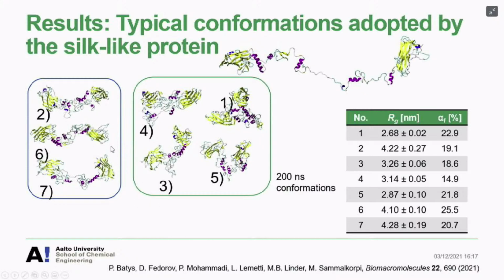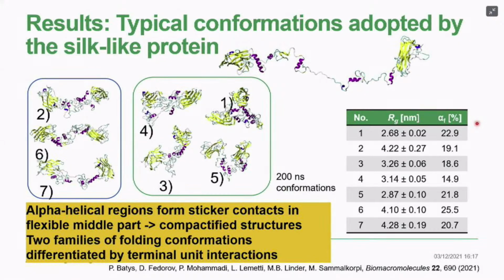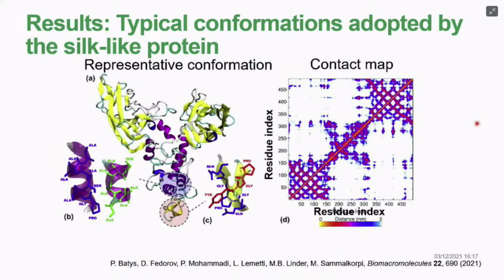There are two families. In one, the proteins are extended, but the middle parts are together here. And then the other family, where also the CBMs are together. So essentially the radius of gyration falls into two sets in those intrinsically disordered segments. And also the fraction of alpha helices, let me get the laser pointer again, is varying depending on what the family is. The alpha helices form sticker-like contacts and compactified structures, and then they differ by how the terminal unit interactions are. I can analyze this further. So this is pretty much consistent with what I just said.